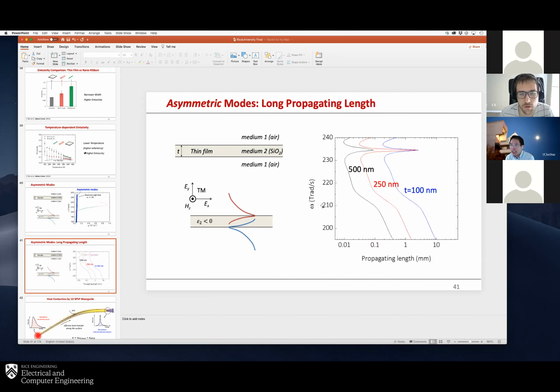Yeah, that's a very important point actually. If we are talking about, let's say, clean silica, where you have just surface roughness, maybe on the order of a nanometer, then the propagation of this mode is not sensitive, simply because the wavelength, a few microns, is much larger than the surface roughness. However, it depends on the lifetime of both the photon and the optical phonon. If the surface has defects that absorb photons, for example certain metallic residues or intentional metallic coating, which is something we are trying to do, then you can greatly reduce the lifetime. But just geometrical variation like roughness will not be too sensitive because of the long wavelength. I see. Yeah, thank you. Sure. Thanks.